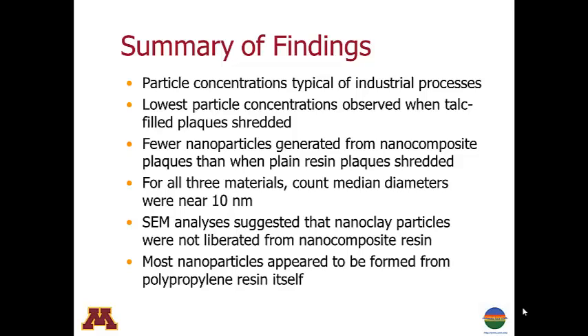To summarize, our findings indicate that the particle concentrations that we measured are typical of levels of particles found in industrial settings. The lowest particle concentrations we measured were when the conventional talc-filled polypropylene resin plaques were shredded. We observed fewer nanoparticles being generated from the nanocomposite resin test plaques than when the plain polypropylene resin plaques were shredded. For all three materials, the count median diameters of the particles generated during shredding were about 10 nanometers in diameter. SEM images suggest that the nanoclay was not liberated from the nanocomposite resin. Instead, most of the nanoparticles appear to be formed from the polypropylene resin itself, perhaps by condensation of polymer vapors produced by heat when the test plaques were shredded. This hypothesis for particle formation requires further investigation.